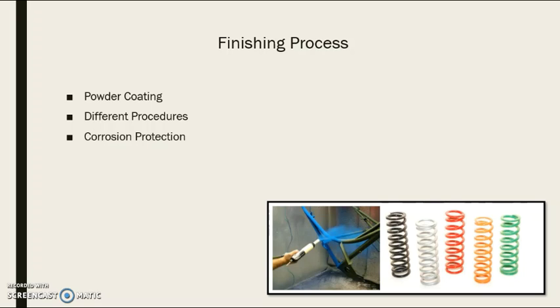The phosphate coatings are applied by dipping the metal into the solution of phosphoric acid and phosphate salts, or having the solution directly sprayed onto the material. The chemical reaction between the solution and the metal forms a layer of insoluble crystalline phosphates. This process gives a base protection to corrosion and helps with adhering the powder coating to the metal. The powder coat is typically applied by a process where high voltage is applied to the particles as they are sprayed, so that they stay on the metal until it is heated and the powder melts, forming a layer on the metal to further protect from corrosion and rust.